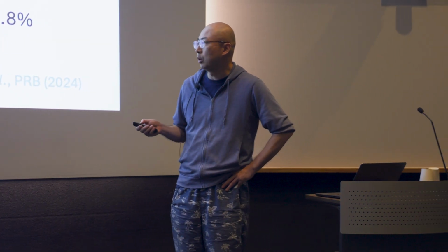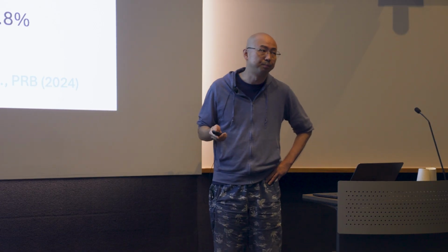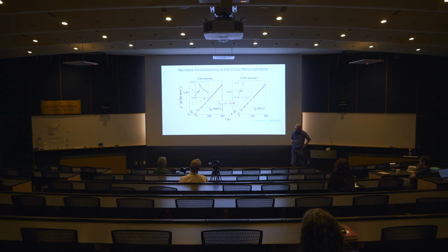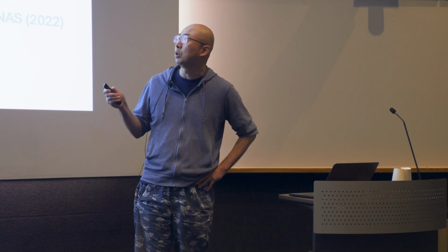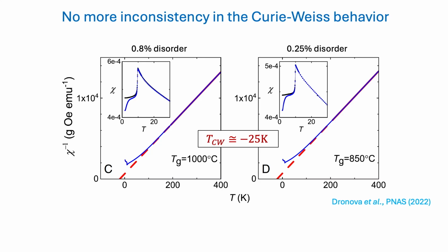We proved that, instead of all the spin frustration people talk about in this material, this system is actually a long-range antiferromagnet. Now you ask, what about the earlier discrepancy with a ferromagnetic-type Curie-Weiss temperature? It turned out that it's no longer there. If you measure our crystals, we have a Curie-Weiss temperature in the negative, minus 25 Kelvin. Compared with the peak temperature of 10 Kelvin, the frustration ratio is only 2.5. So this is not even a strongly frustrated system. It's mildly frustrated at most. So we no longer have any discrepancy.